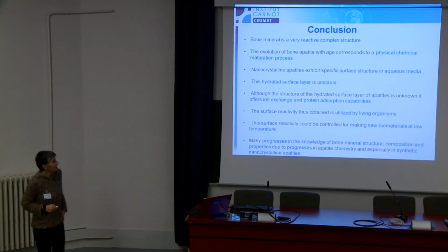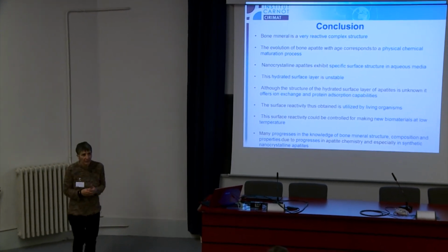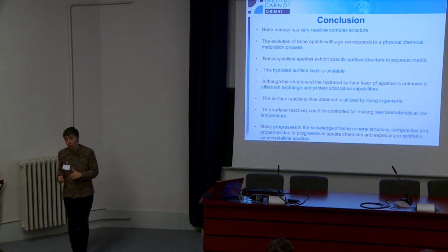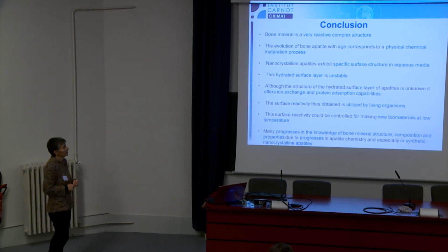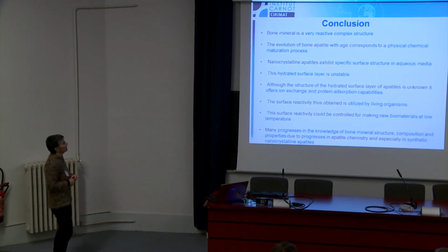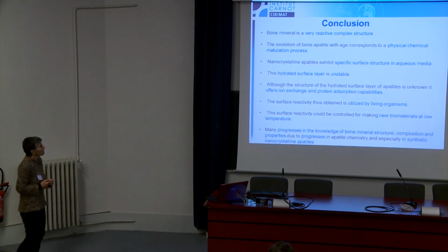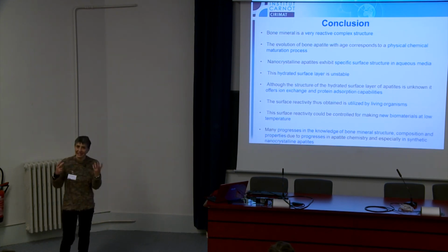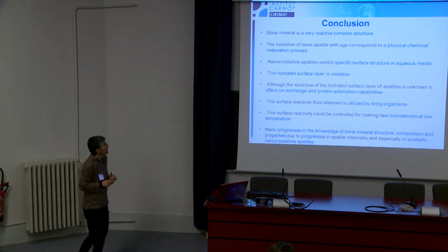So to conclude my talk, okay, sorry. I think you see that bone mineral is a very reactive, complex compound and structure. The evolution of bone apatite with age, we show, corresponds to a physical-chemical maturation process. We show also that nanocrystalline apatite shows a specific surface structure in aqueous media when it is hydrated. We show that this hydrated layer is unstable. It can disappear upon drying.